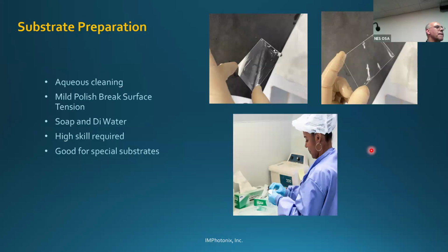Do you use the same materials available? Yes and no. You can produce the same films, but not use the same materials. Caitlin is our principal scientist who's been working on the sputtering, and she's been experimenting with different materials. One of the things is tantalum pentoxide, where you buy tantalum pentoxide from Materion. With pulse DC magnetron sputtering, you can't evaporate tantalum pentoxide because it will insulate. So you start with tantalum.